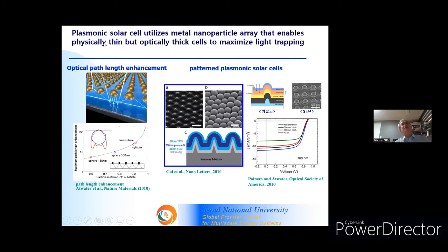Plasmonic solar cell is another good example showing the importance of three-dimensional nanostructures. Plasmonic solar cell utilizes a metal nanoparticle array that enables physically thin but optically thick cells to maximize light trapping. Through this array of metal nanoparticles, light can be trapped inside the thin film solar cell. Therefore, path length of the light can be greatly increased and power conversion efficiency can be significantly improved.